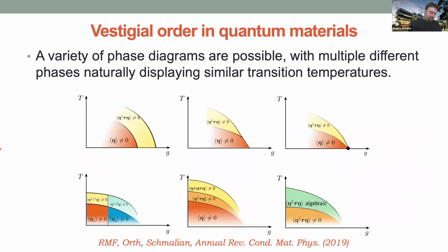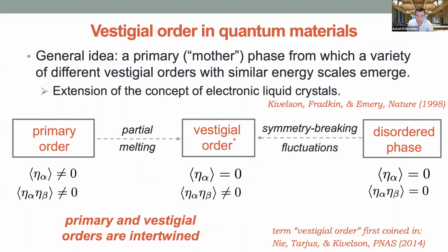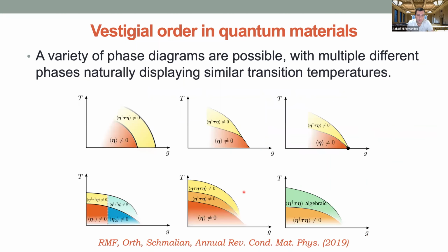So now that we have this idea, a key point, as Dimitri just mentioned, is that I need fluctuations. If you do mean field, this never happens, so you need to go beyond mean field, but it's still phenomenology. You can get a rich variety of phase diagrams. The key point is that these two phases, whatever you do, end up having similar transition temperatures—they have similar energy scales.